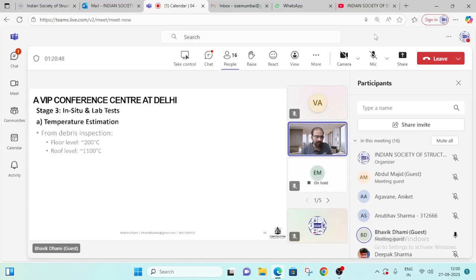Now, doing some NDT tests and lab tests, we were able to find from the debris itself what kind of temperature they were exposed to, approximately. Floor level was around 200 degrees Celsius and roof level it was 1100. Due to no ventilation or the confinement, the temperature might have risen to that sort of temperature. It is an approximate temperature from the inspection they carried out, and from core tests they were able to identify what sort of MPa they got from columns, beams, and slabs on an average basis. So columns at 16 MPa, beams at 18 MPa, slab at 17 MPa.